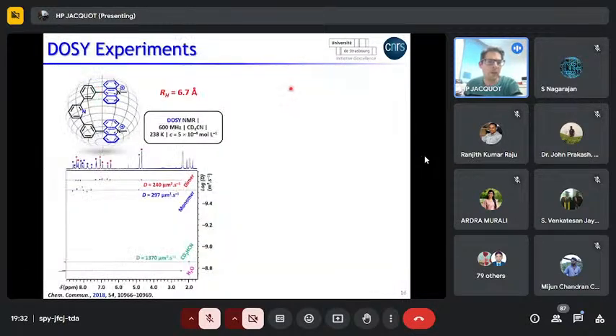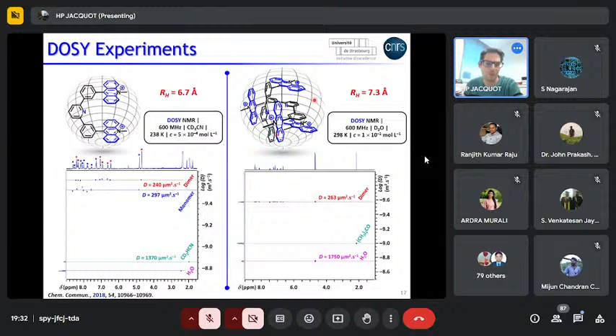Another proof of the dimer formation was provided by DOSY experiments. So actually, under conditions where you have the monomer and the dimer, so in acetonitrile, under dilute conditions and at low temperature, you do have 2 diffusing species, one which is faster than the other one, which is the monomer. And thanks to the diffusion coefficient, we can estimate a hydrodynamic radius of roughly 7 angstrom for the monomer and also 7 angstrom for the dimer. This value of 7 angstrom for the dimer was also confirmed by those experiments in D2O. And this value of 7 angstrom is also in good agreement with what we can observe for the solid state structure. So I hope I was able to convince you that we have this dimer in solution in different solvents.